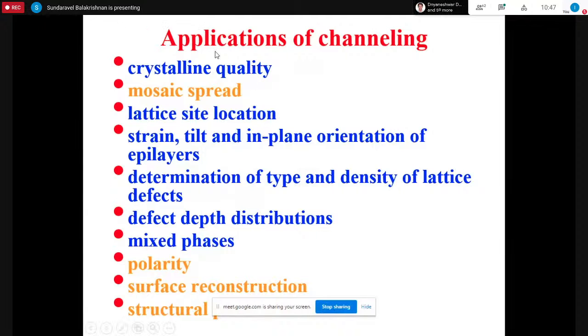As such, there are many applications of this ion channeling, and I will discuss some of these applications, like determining crystalline quality, determining how much the mosaic spread is, and lattice site location of an atom. For example, in silicon we can dope with either p-type or n-type dopants like boron or phosphorus, and n-type or p-type silicon works only when the dopant impurity atom stays exactly in the substitutional position. That is, you are taking a silicon atom out of the lattice position and replacing it in that location with the dopant. Then only your dopant property will be there. So you can find whether your dopant impurity is exactly sitting in a substitutional or interstitial position.